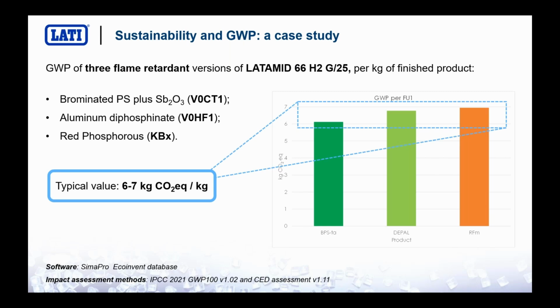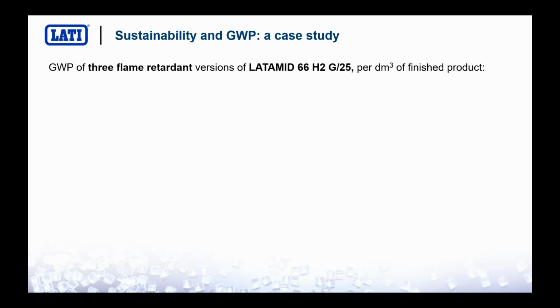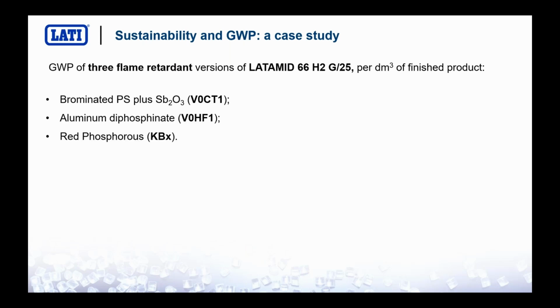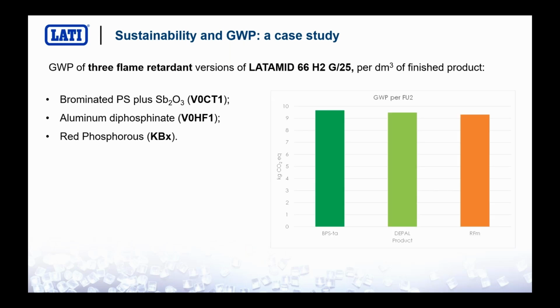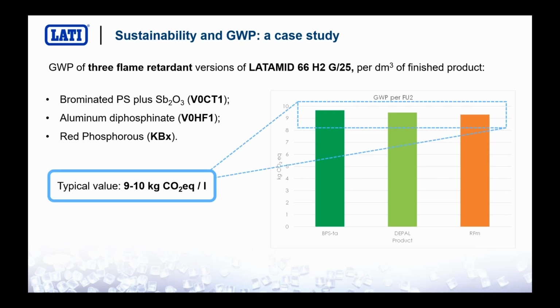If we move from this evaluation per kilogram of finished product to the evaluation per cubic decimeter or liter, so the volume of the application, then we will see that these numbers are skyrocketing because of the density of the material. So per every liter of the foretold flame retardant materials, the global warming potential is increased to 9 to 10 kilograms of CO2 equivalent per liter. So you see how impacting is every kilogram of flame retardant plastic that you put in your project.